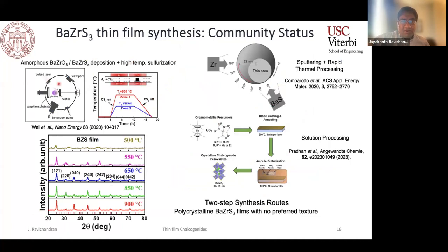After the lot of interest in the bulk properties of these materials, there's a lot of work that started emerging in thin film growth. There were two-step processes that were developed where you deposit the zirconium oxides and then you sulfurize them in a high temperature sulfurization system using CS2 or other sulfurizing agents. There were a lot of improvements that allowed people to grow fairly crystalline materials down to 500 or even 400 degrees Celsius. There was some work on the solution processing of these materials, which lowered the processing temperature significantly. There's also work on sputtering and then rapid thermal processing to get these structures. Invariably, all of these techniques involve two-step processes, sometimes high temperatures, and not always fairly large grained or even high crystalline quality materials with these approaches.